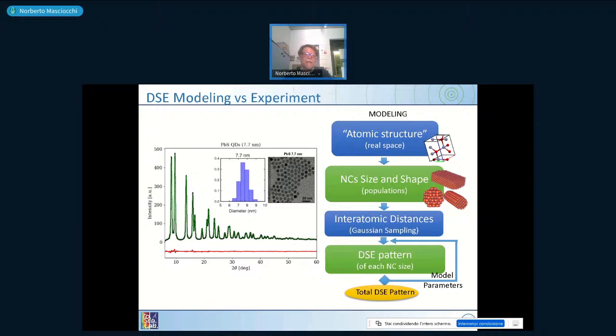You probably don't see the difference because they overlay very well. And the difference plot, the difference between the matched pattern and the matching one, so the calculated and observed one, is the red line you see down there. And you see the red line is nearly flat. It means that by using our parameters, and among which you have also the distribution of your sample sizes, you get a very nice fit.